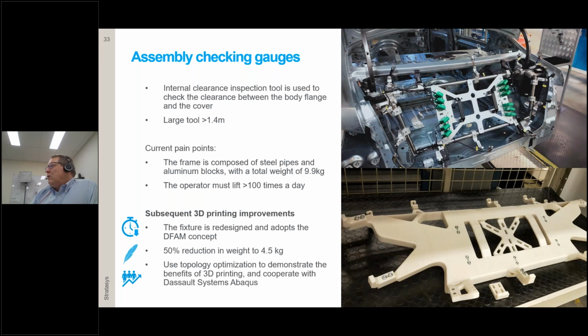Here we're combining a very large tool with a total length of above 1.4 meter. You have a huge frame made out of many components. You combine them into a 3D printed framework, and all your end contact points are shimmed, doweled, and of course then screwed, and before that measured to accuracy. So you can achieve much better accuracies. I have been selling these kind of checking fixtures for many years. And in the automotive industry, surface contacts have an accuracy of plus minus 0.1, and master location points will require plus minus 0.05 millimeter. This can only be achieved if you can fine adjust those location points. This cannot be printed still today.